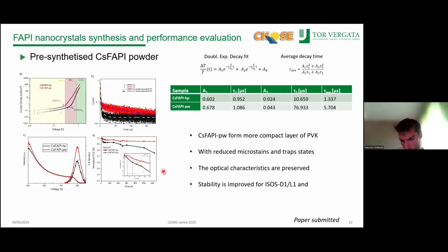It's still poor stability, let's say, but we continued the test till 1000 hours, and we saw that our CsFAPI-pw at 1000 hours lost less than 40% of its initial efficiency, whereas the high purity precursor lost more than 80% after 1000 hours. Those are, of course, our results. I also have to highlight that in the perovskite, in this case, there are no additives except for MACl. So we just compare the bare films as they are.